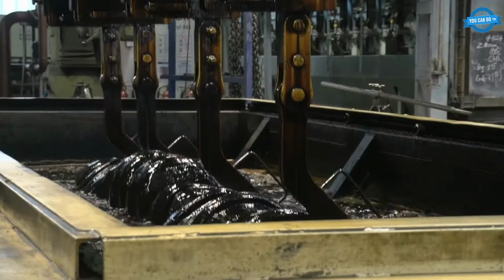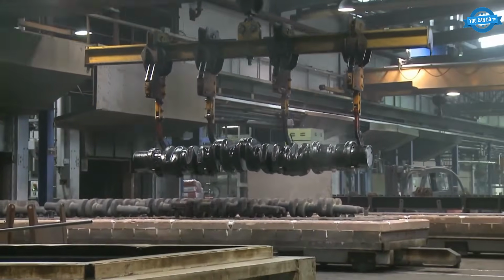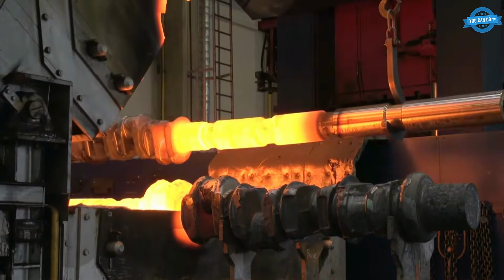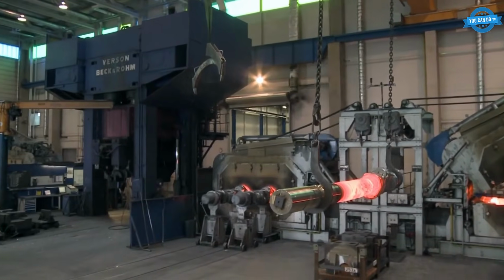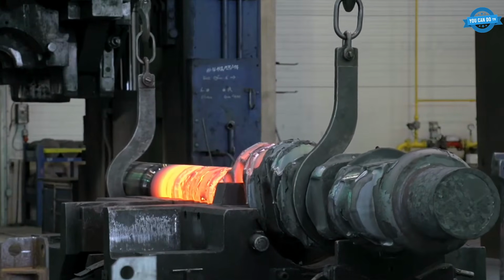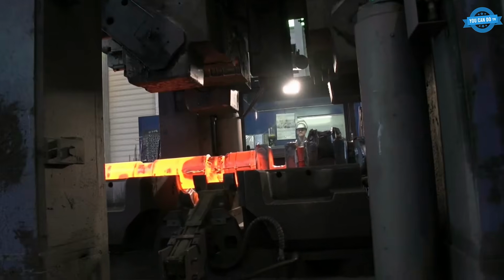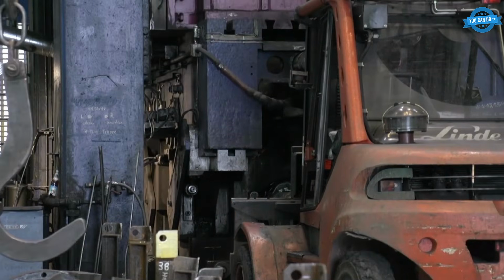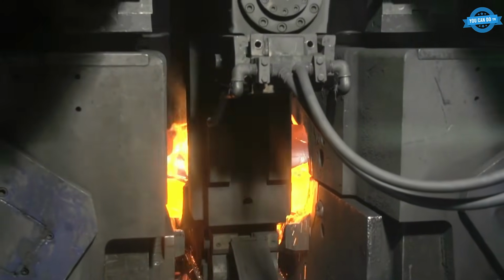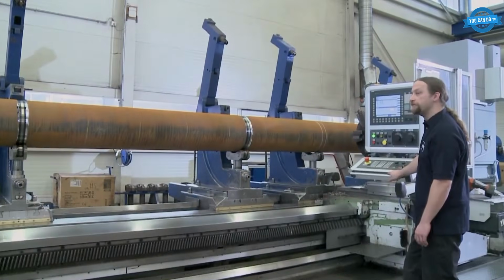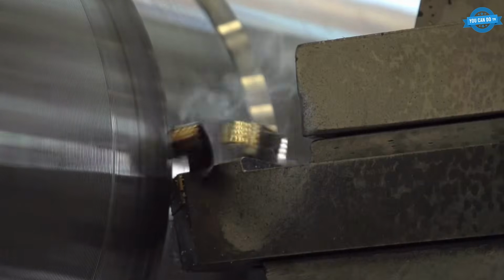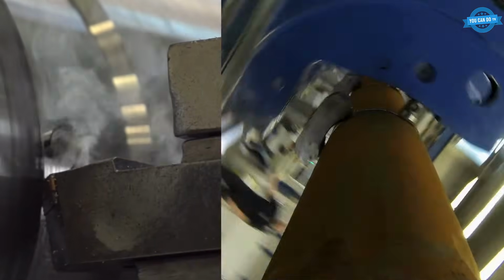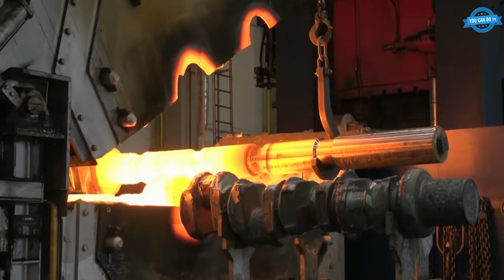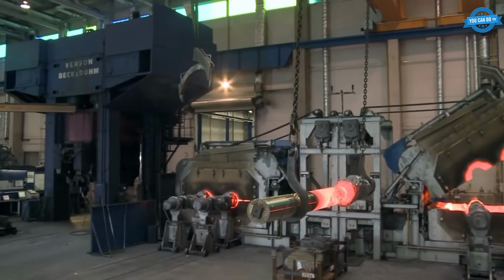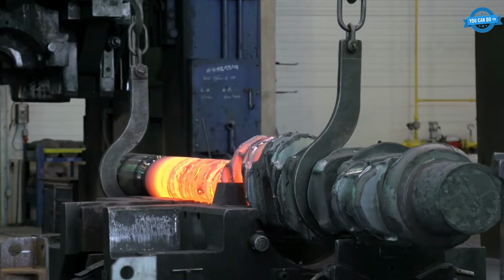The starting point is a clean alloy steel ingot that has already been controlled for its chemistry. The ingot is heated to forging temperature, brought to the press, and worked under hydraulic pressure in repeated heat and press cycles. A manipulator on the floor grips the workpiece and rotates it between strokes, so the press can work the material from every direction and drive the deformation deep into the center.